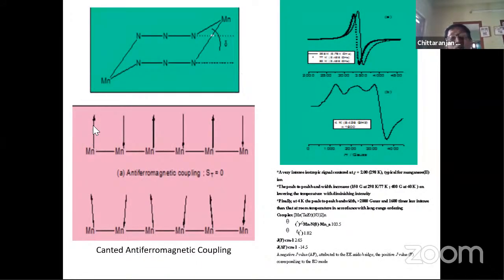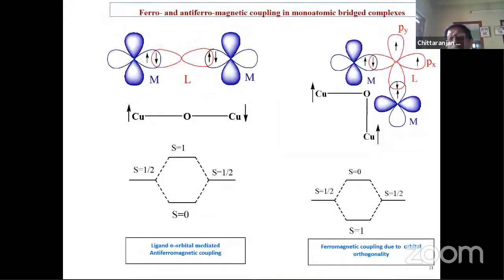And you know, these unpaired electrons, if they undergo the opposite spin process, sometimes the structural strain is released by changing the spin direction or tilting the spin, which is known as spin frustration. And that spin frustration may be responsible for this ferromagnetic behavior. So spin frustration, spin bubbling, and so on, a variety of spin stresses are developed because of this structural strain. Not going into detail of it, some spin interaction and its geometry is responsible for its magnetic moment.